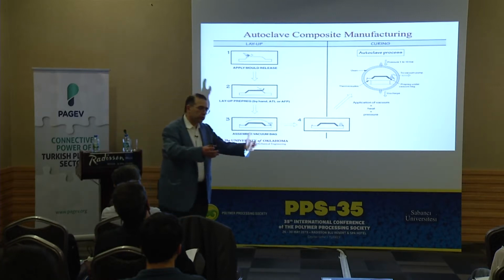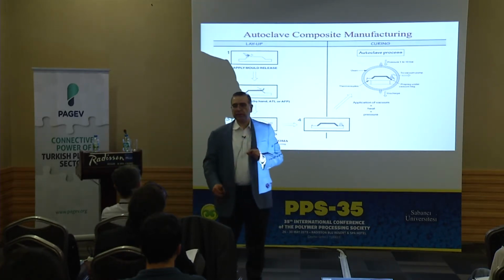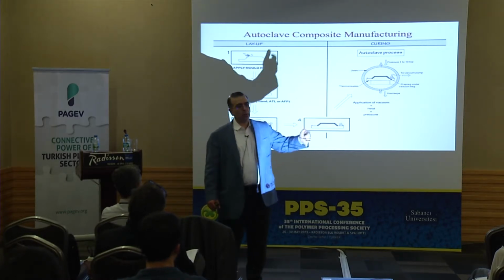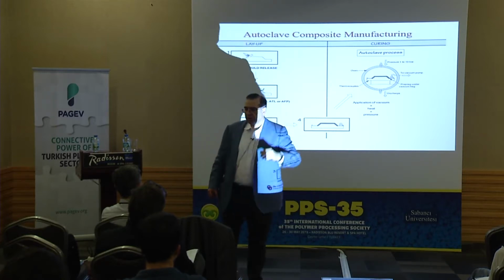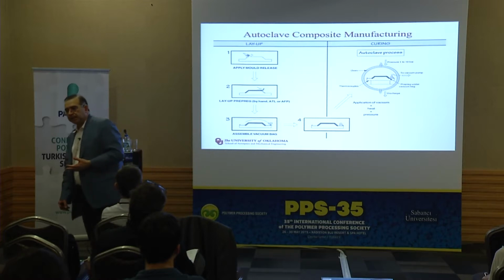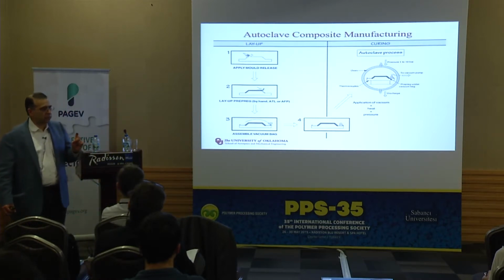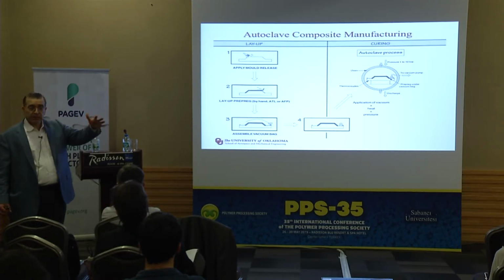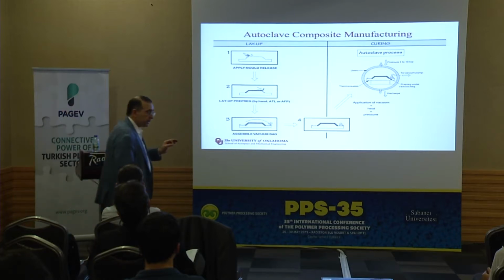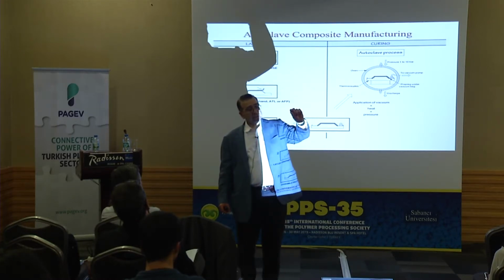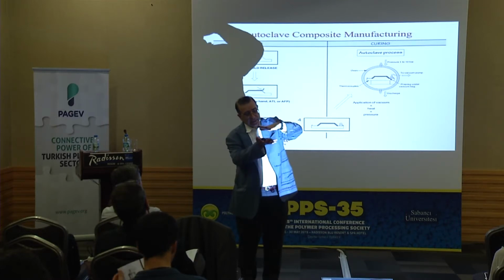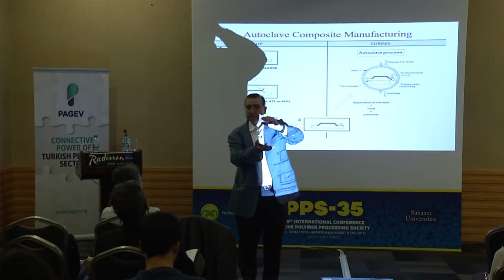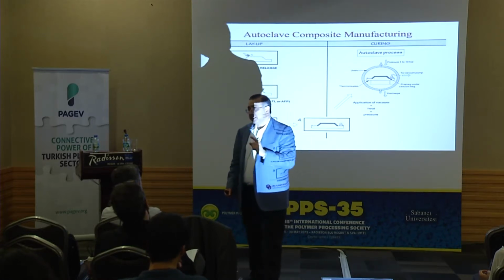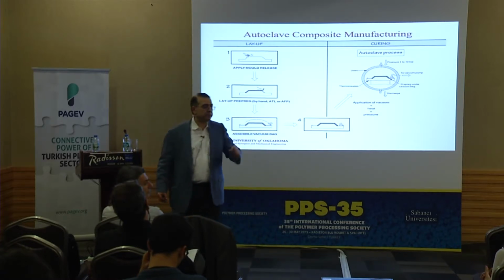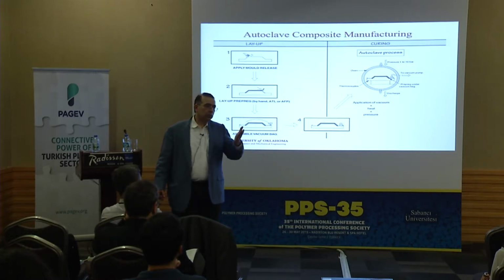Same tool plate, you put it in autoclave, you cure it at, again, 100 kilopascal or 90 kilopascal vacuum pressure, but on top of that, autoclave is pressurized to 200 or 300 kilopascal. So you have essentially on top of the vacuum pressure, 3 times as much pressure applied to your laminate during cure. As you heat it up, resin starts melting. So with that added pressure, you will have, let's say, much better consolidation. These layers will get close to each other, right? And then your laminate at the end will come out to be, instead of 2 millimeter, 1.75 millimeter.